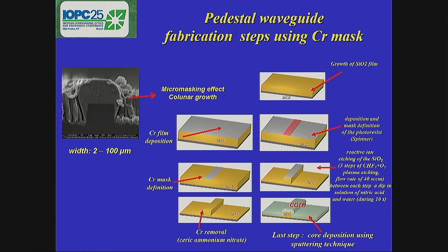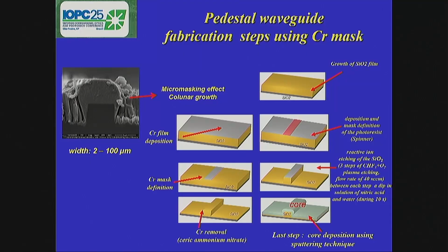Now, I will just show you the evolution of the process over the years very briefly. At the beginning, we used a chromium mask to prepare our patterns, but we had some problems. Sometimes the chromium is not totally removed, and we have the well-known micromasking effect, which is this columnar growth that compromises the guiding because the columns play the role of scatterers. But well, these are the steps used in the clean room. I'll not go into detail, but normally we take 1 week to finish. We have a protocol for that, but sometimes we change some of the steps in order to obtain waveguides with better performance.